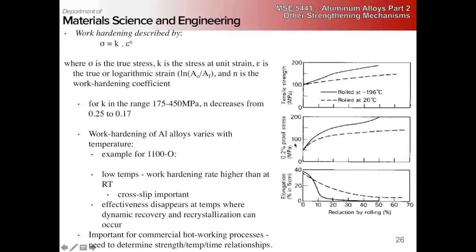And this higher work hardening rate at low temperatures is because we don't have dynamic recovery and recrystallization. Right? Our thermally activated recovery mechanisms are not available.